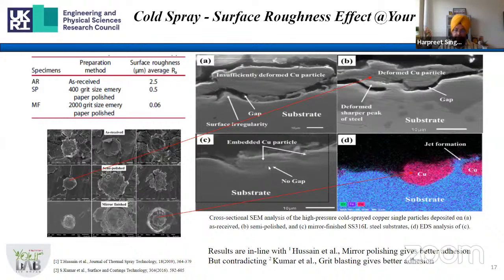In fact, we established that there was no hindrance to the particle coming in from peaks on the surface, whereas we could see peaks on the semi-polished surfaces, which could absorb a lot of the energy of the particle to deform. So these sharper peaks deform, and that is why the energy of the particle is dissipated, and there is always a kind of gap between the coating and the substrate. But here you can see the whole energy of the particle is getting used to get adherence on the surface. He established this with the help of SEM. He did a lot of SEM analysis on that.